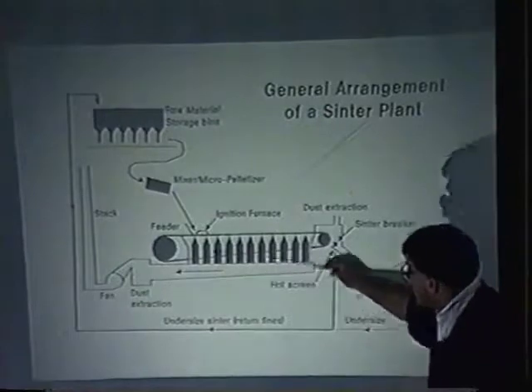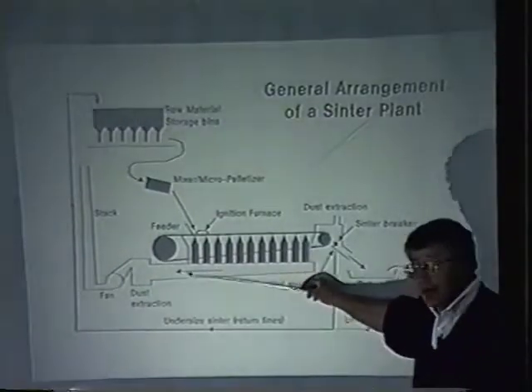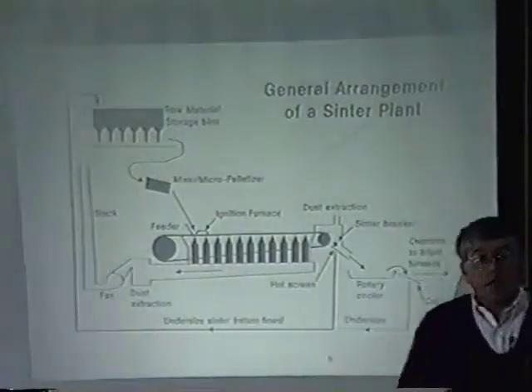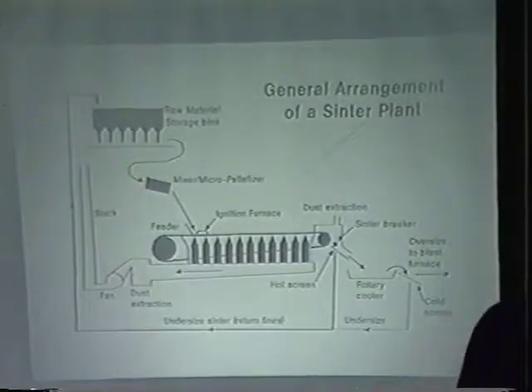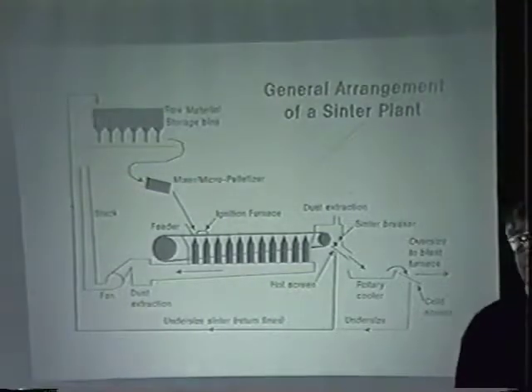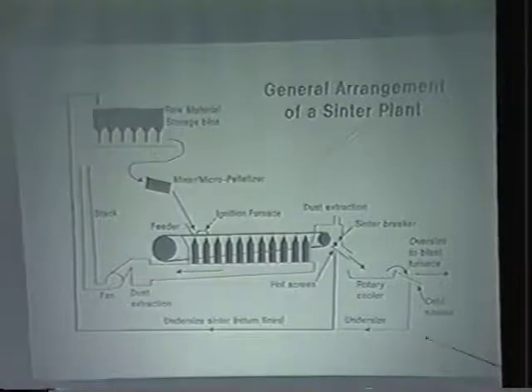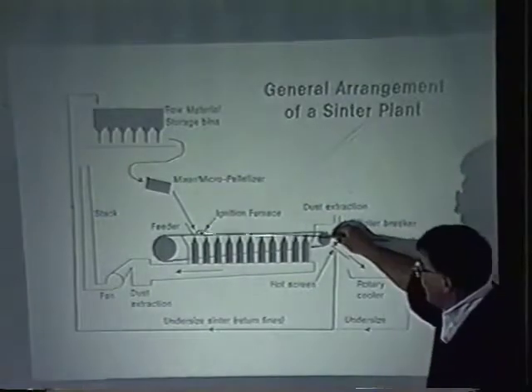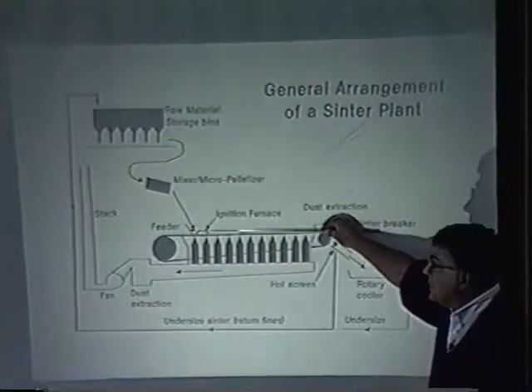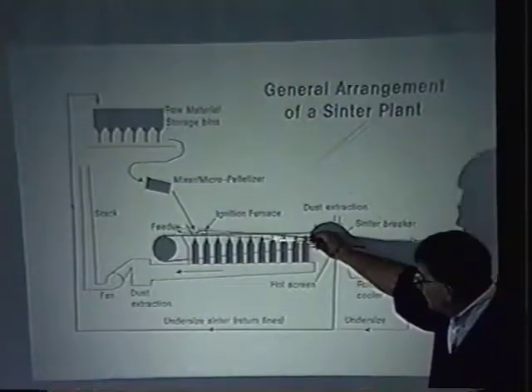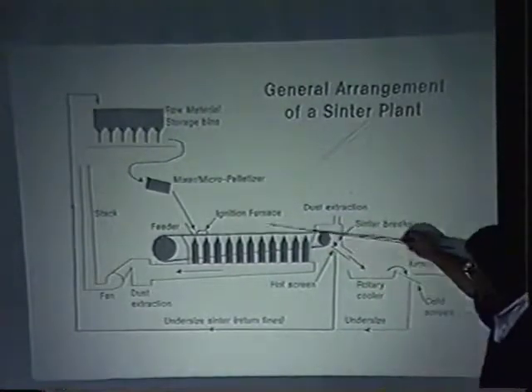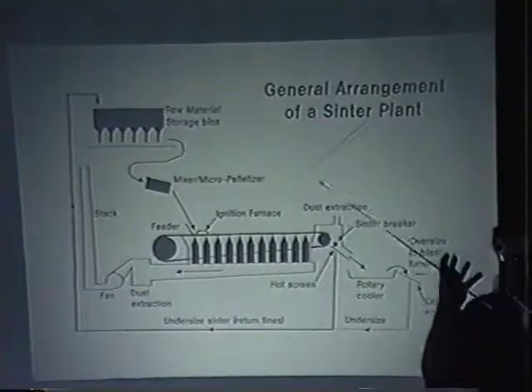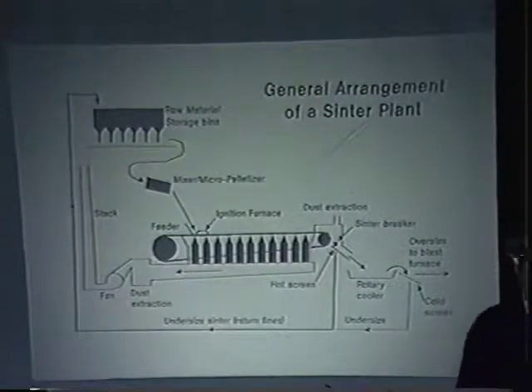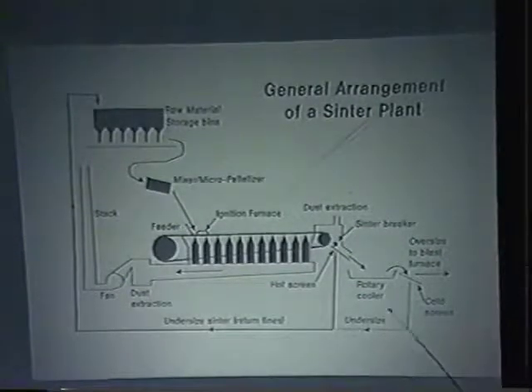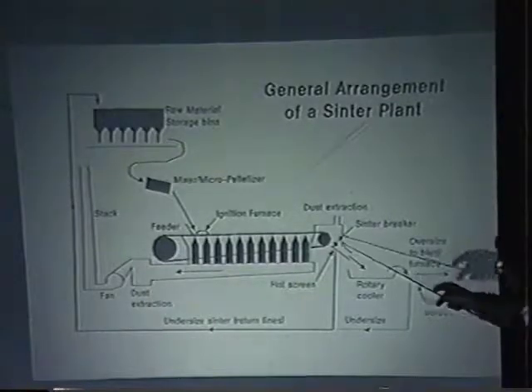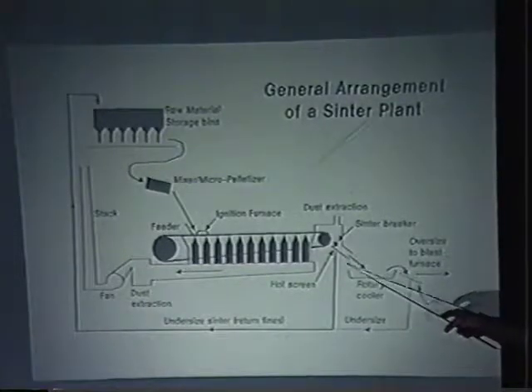Now underneath here is a set of wind boxes connected to a fan. And it's sucking air down through that sinter strand. And as it sucks the air, it's drawing the combustion down through the bed. So by the time it starts here till it gets to the end of the strand, all that sinter has been heated and cooked. Okay? Then it comes off the strand and we screen it.